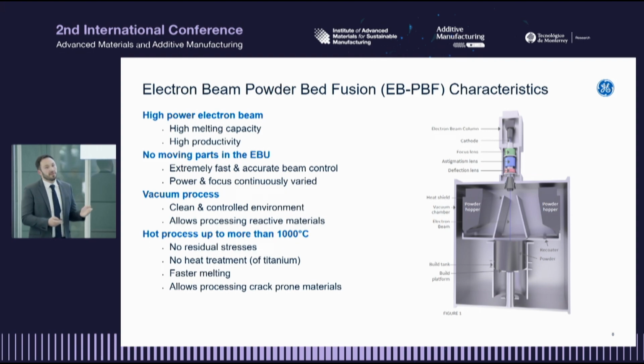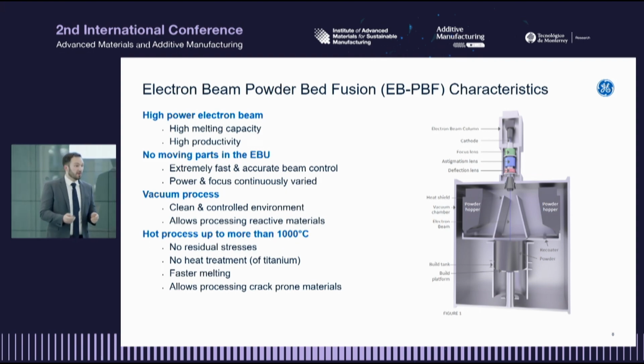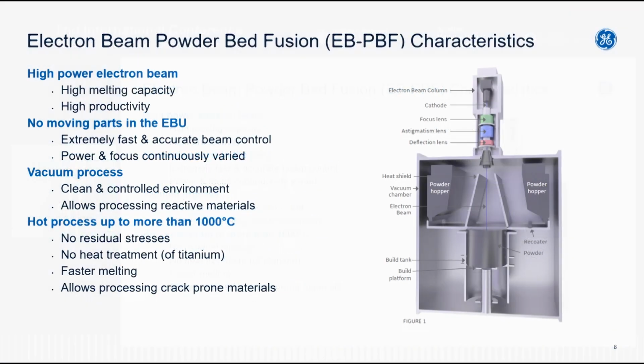And the final one that's worth mentioning is beam power here. These beams are between 4.5 and 6 kilowatts of power, and because of that reason, you can actually penetrate further into the powder bed than you would with a laser beam. To that end, we can use a larger particle size distribution, and therefore the powder is safer. Our titanium powder is not a combustible dust, nor is it a flammable solid because of its size.